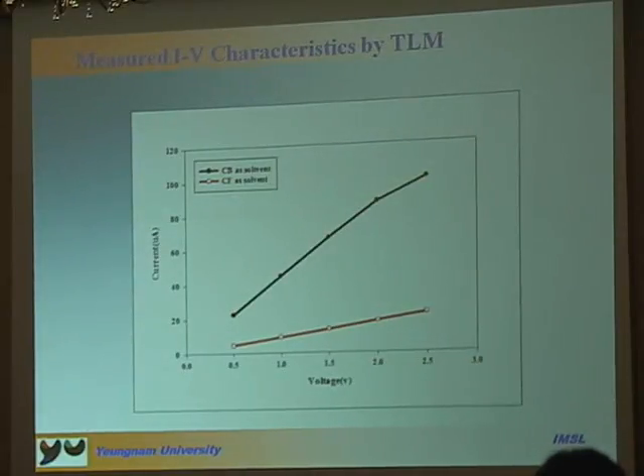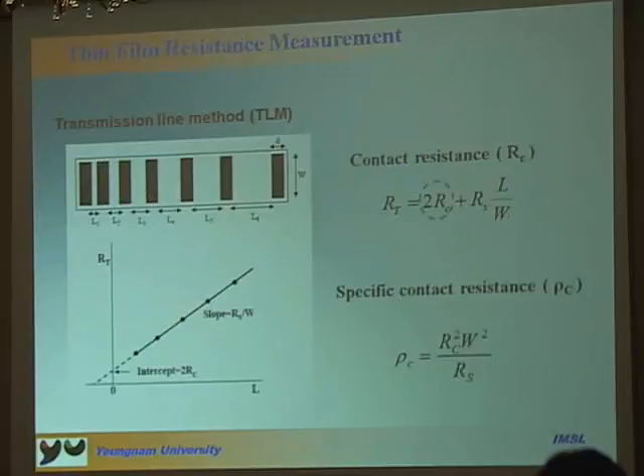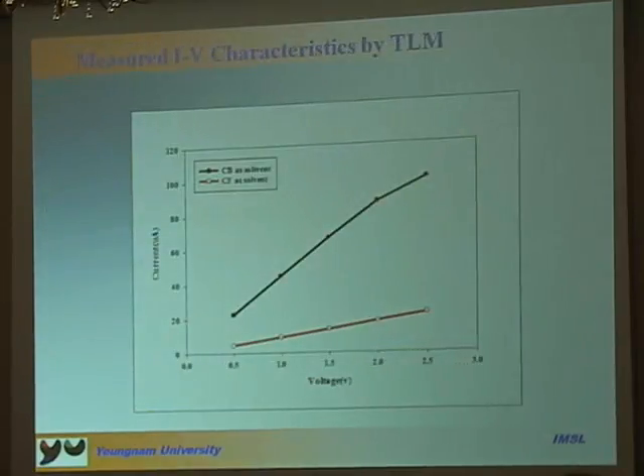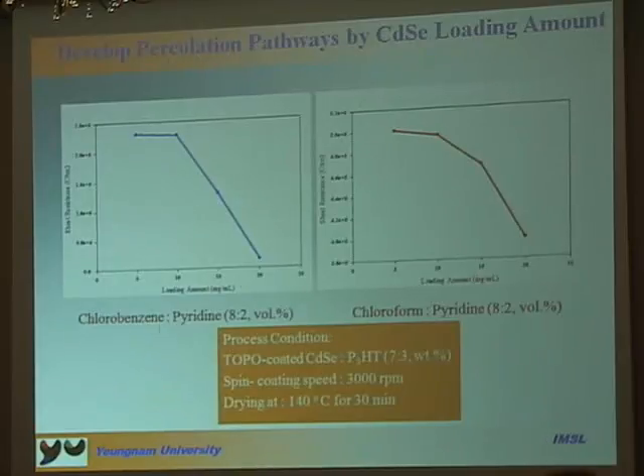Now let me talk about how to measure the resistivity, the contact resistance. In this figure, we first measure the total resistance between two pairs. After that we get a plot like this, and from the plot characterization we can calculate the total resistance, contact resistance, and sheet resistance. So after that we can know the specific contact resistance. After measuring the resistance, we get some data like this.